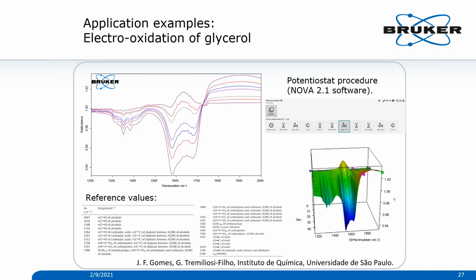As you can see here, we can obtain spectra at different potentials, subtract the spectrum at 0 potential, and see all the bands. These are pretty wide bands consisting of many smaller bands, and we can assign all the individual bands. We can do a spectrum deconvolution and assign different bands to different molecular structures, and you can see at the bottom what kind of reference values we can use for different assignments.